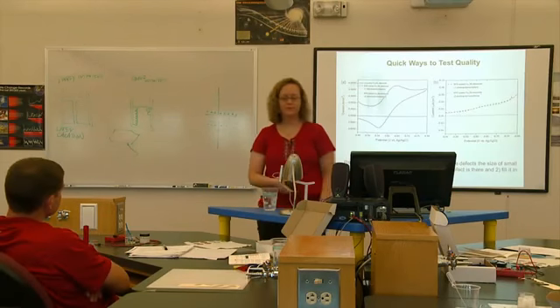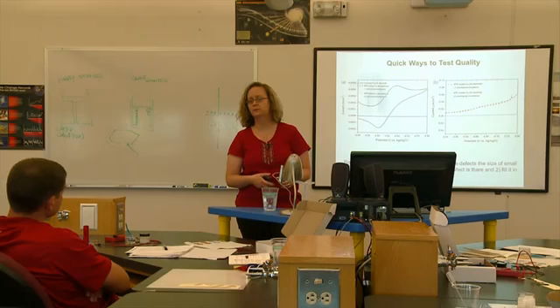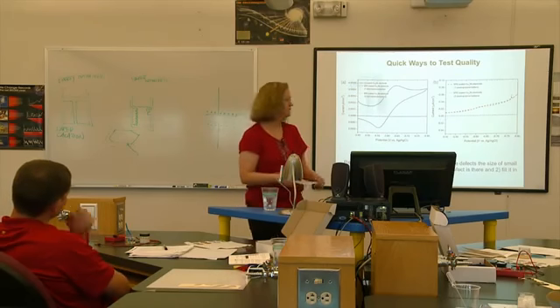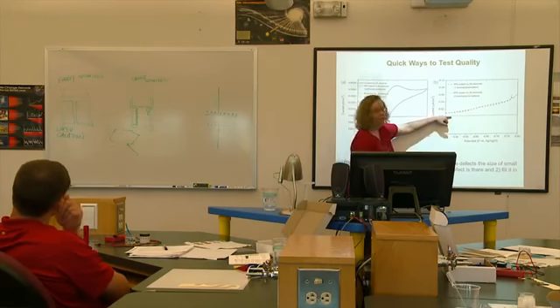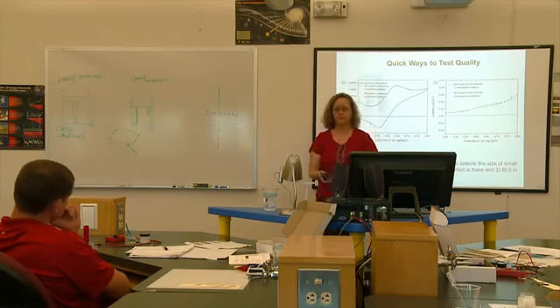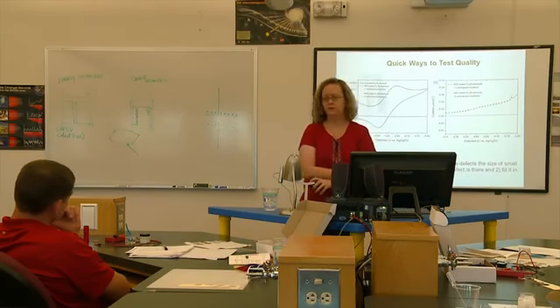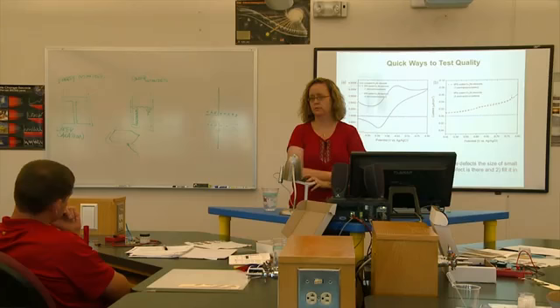So now that we've optimized our polymer deposition, the guys are at about 1 out of every 45 has a defect. And if they see this flat line, when they put the full battery together, out of batches of 50, we're at 50 out of 50 that don't short. That doesn't mean they work great for other reasons, but it means they don't short. So now it actually works. This idea actually works.